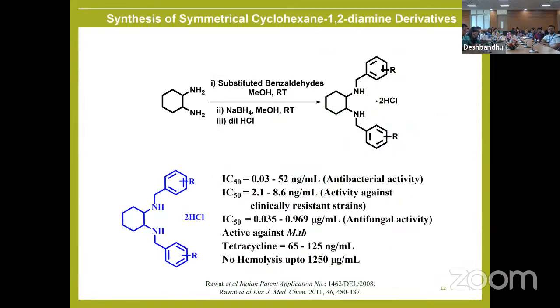Initially, we synthesized symmetrical cyclohexane diamine derivatives. We took cyclohexane diamine and treated it with different benzaldehydes, and those Schiff bases were then reduced, and we got these diamine derivatives. These compounds were tested for their antibacterial activity and anti-fungal activity, and they were also found to be very good anti-tuberculosis agents. These compounds showed no hemolysis up to a very high concentration.